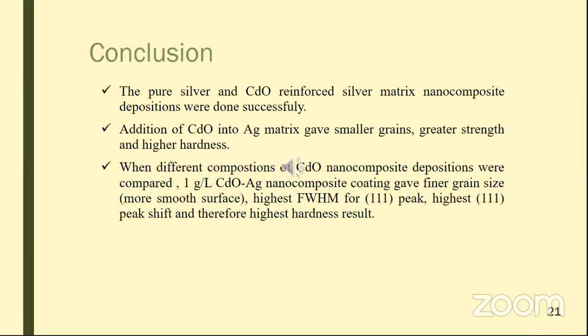There have been studies about preventing the welding problem on contacts with cadmium oxide, but these studies have been in micro size. There is no study in nano size. So the aim of this study, achieving cadmium oxide reinforced silver-based nanocomposite depositions in nano size, is accomplished successfully. And according to the results, addition of cadmium oxide into the silver matrix gave smaller grains, greater strength, and higher hardness.